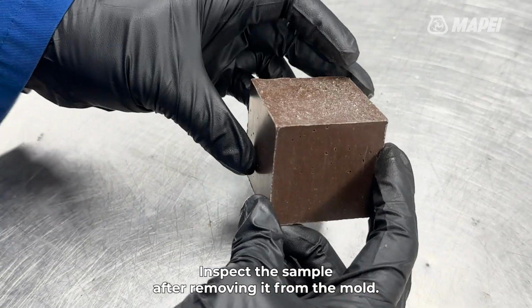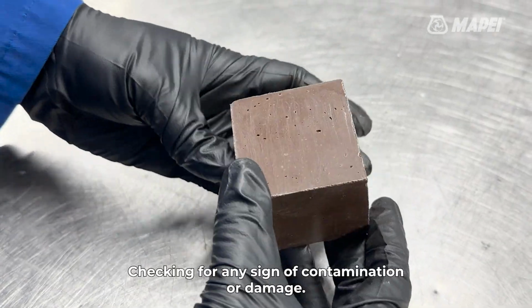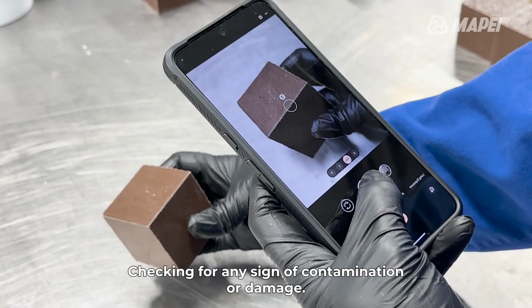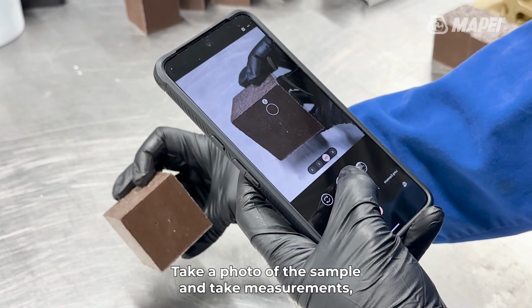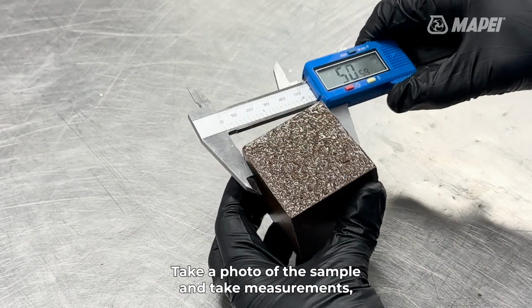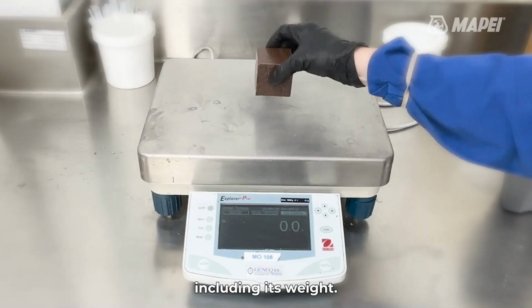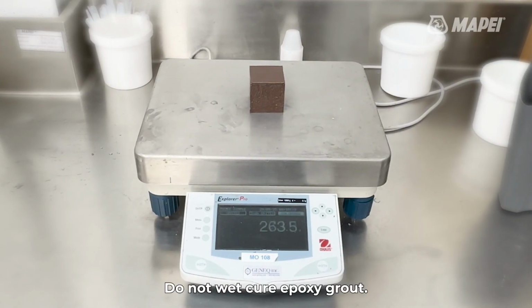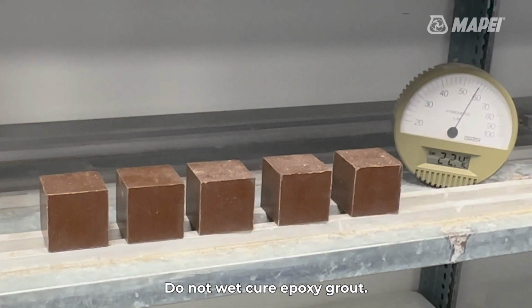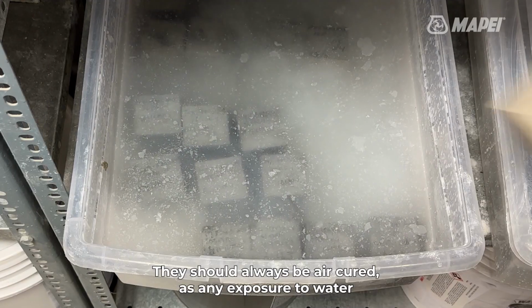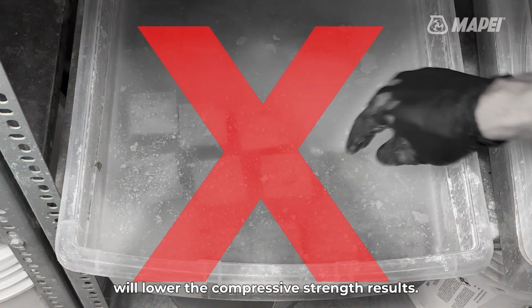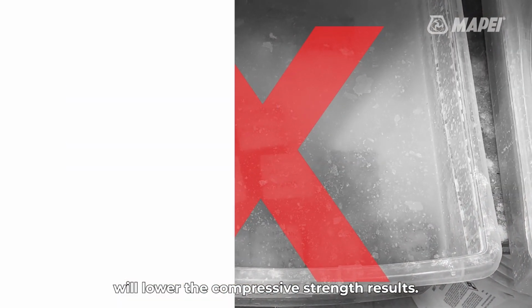Inspect the sample after removing it from the mold, checking for any sign of contamination or damage. Take a photo of the sample and take measurements, including its weight. Do not wet cure epoxy grouts. They should always be air cured, as any exposure to water will lower the compressive strength results.